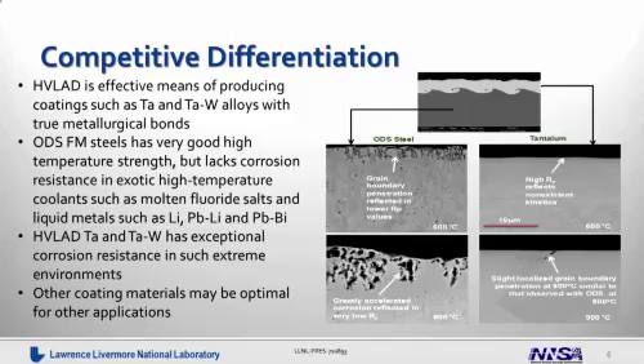In this particular slide, we see the benefits of coating a surface with an HVLAD coating. On the left, you see micrographs of an oxide dispersion strengthened steel, which is good for use at very high temperatures after being contacted with a high temperature coolant, such as a molten fluoride salt. The molten fluoride salt, as one might expect, attacks the ferritic steel very aggressively, leaving the surface very much like Swiss cheese. On the right, we see the same surface protected with a HVLAD coating of tantalum. The tantalum prevents the attack of the oxide dispersion strengthened steel with this high temperature molten fluoride salt.